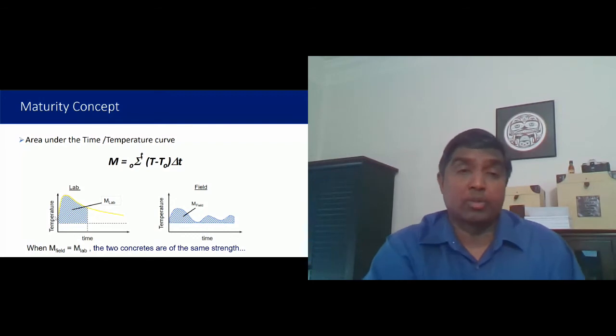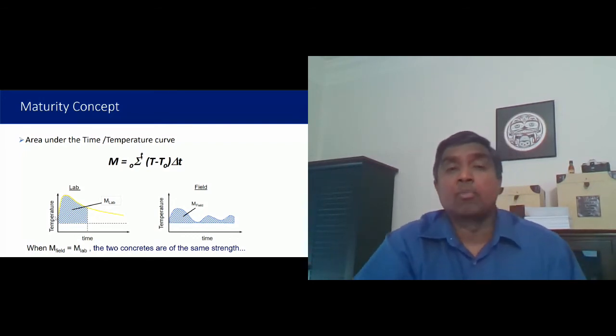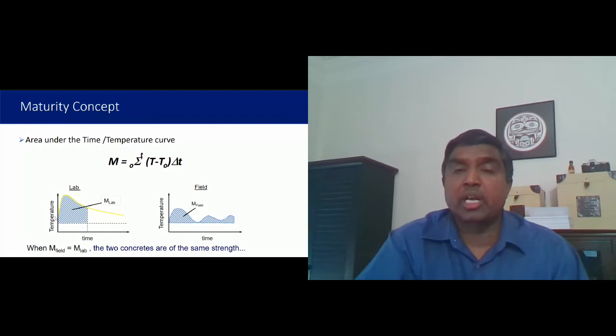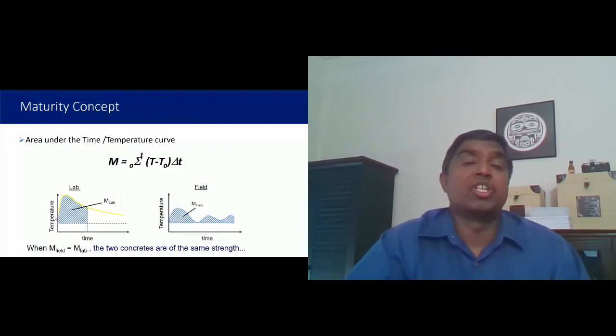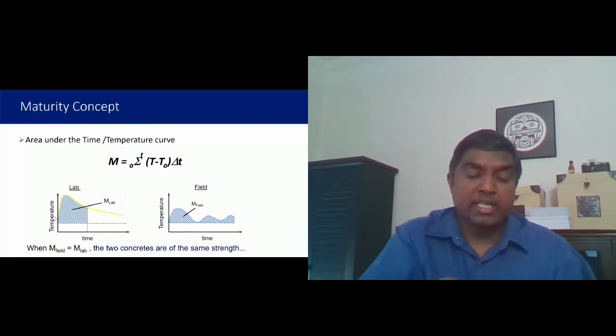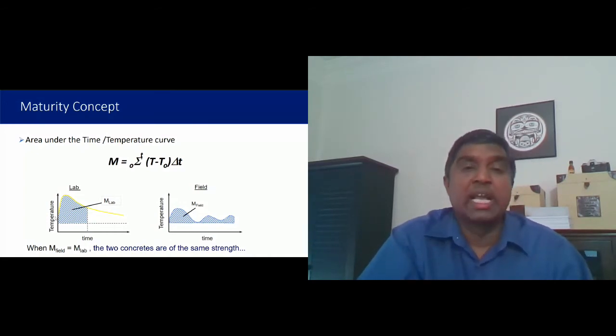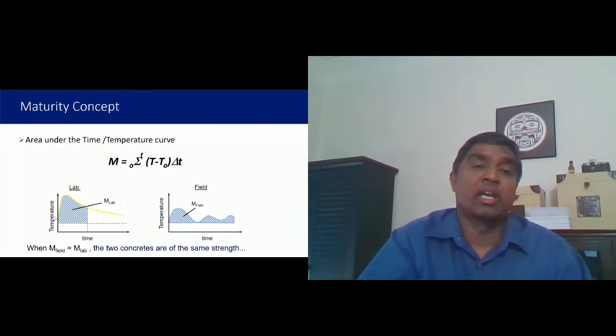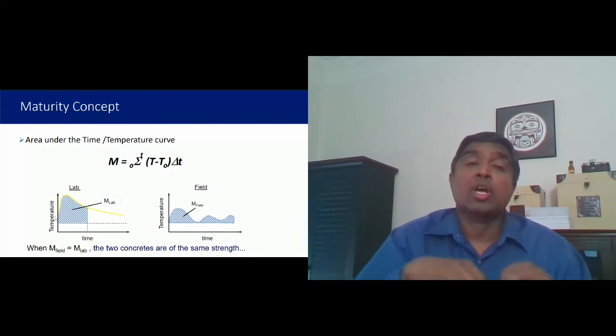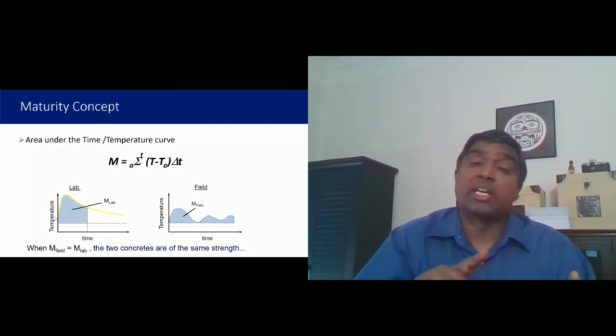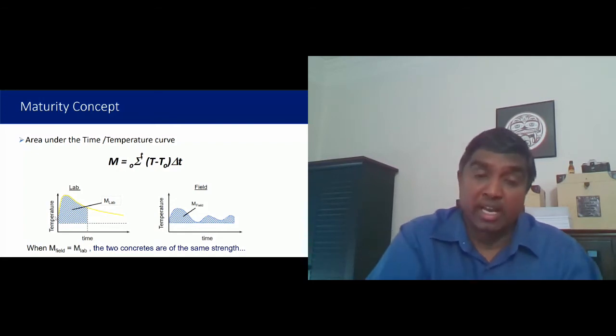So how does it work? I mean, that's the concept, right? So how does it work? Well, this slide in a nutshell shows the overall procedure with maturity. Basically what we do is we make a bunch of cylinders, anywhere from 12 to 15 cylinders. And in one of the cylinders, we put in a temperature sensor. This particular sensor measures temperature. It also measures time. So not only does it measure time and temperature, it can also calculate the area under the curve that I showed in the previous slide.